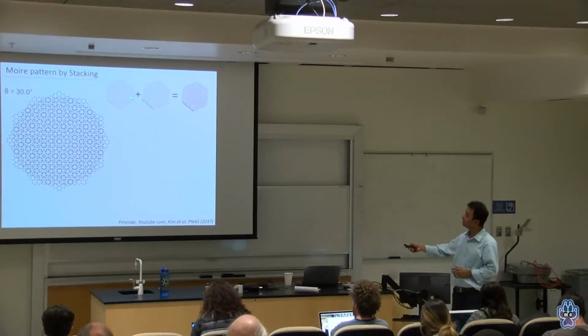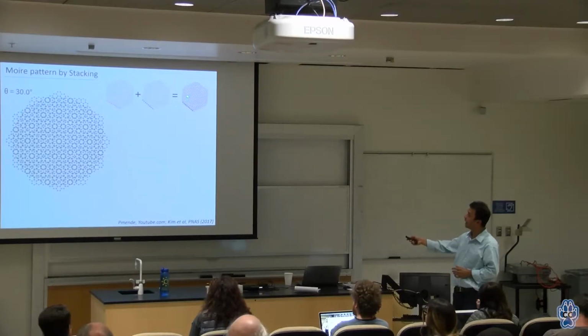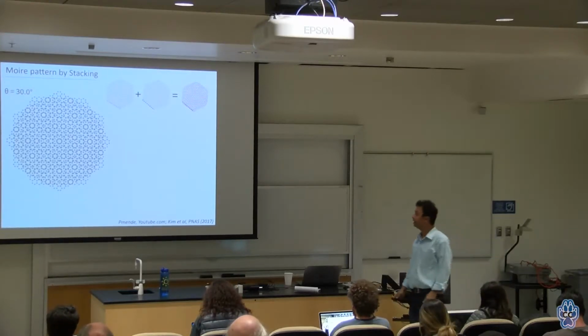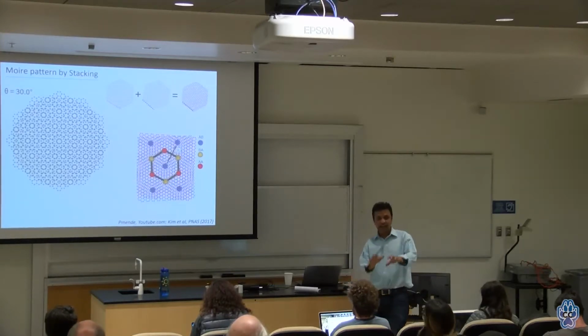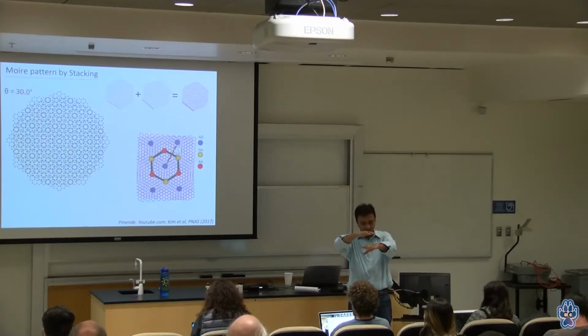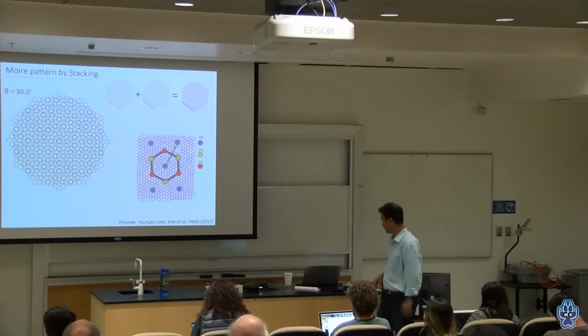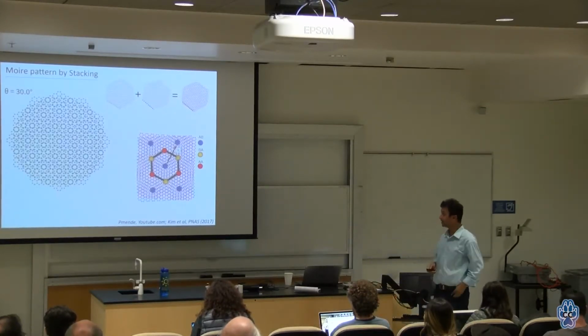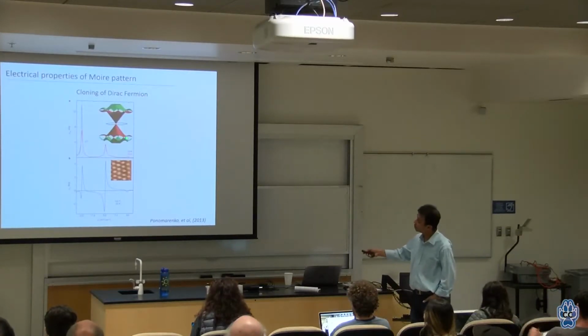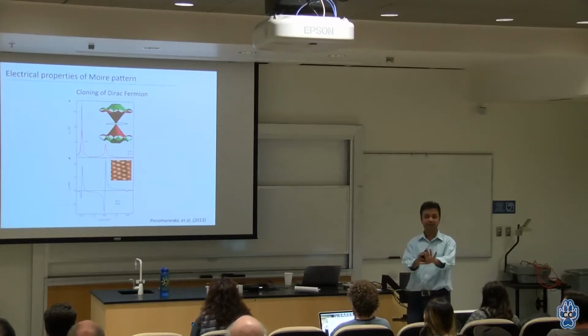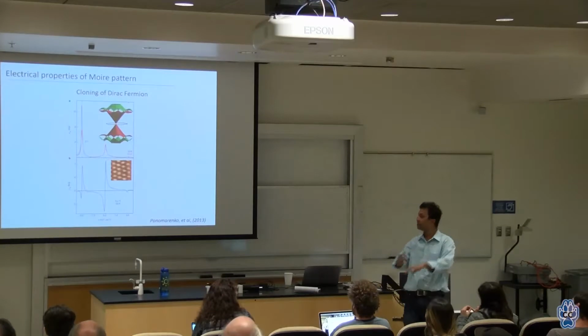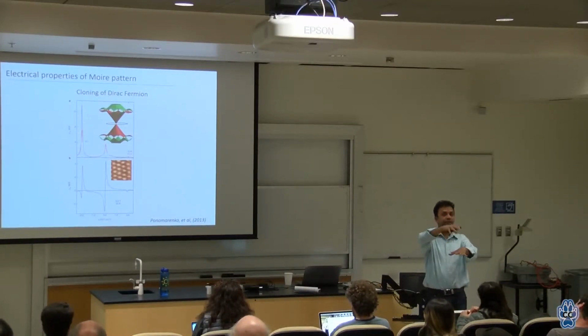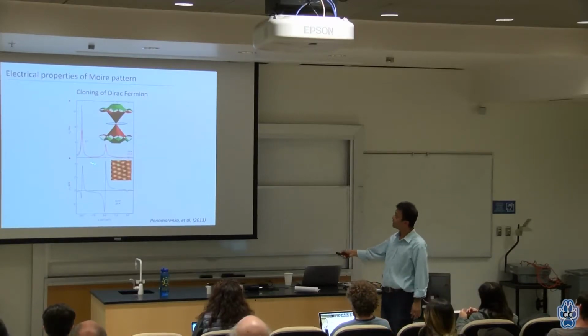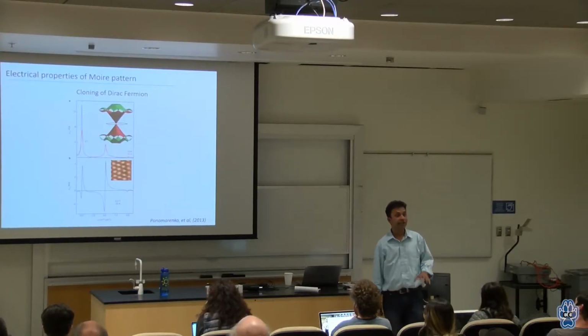So if you go to a slower slide, you have this graphene. If you put it at a certain angle, you can see the angle. You can have graphene here, and you can also have this hexagonal pattern. All right, so you are creating a superlattice with another, right? You have a hexagonal lattice and then put another hexagonal lattice with a larger lattice constant. What would happen is, you remember I showed you at the beginning that the band structure for pure graphene is a conic shape. Now you create another hexagonal lattice, and you create more conic shapes, but at different energy levels, right? Before, I had only one structure. Now I create other structures in the conductance as I change the carrier density.